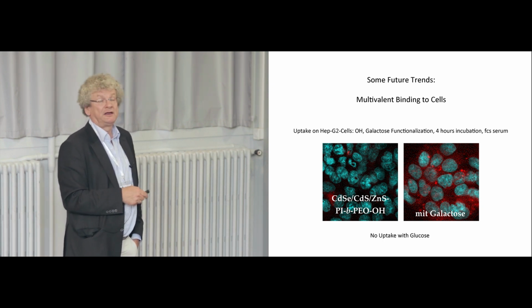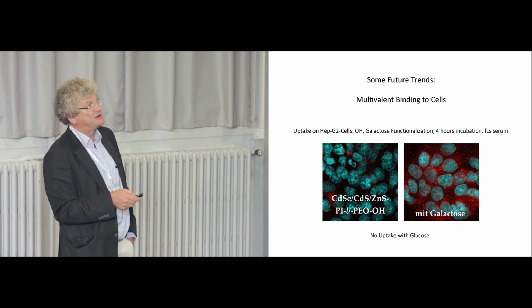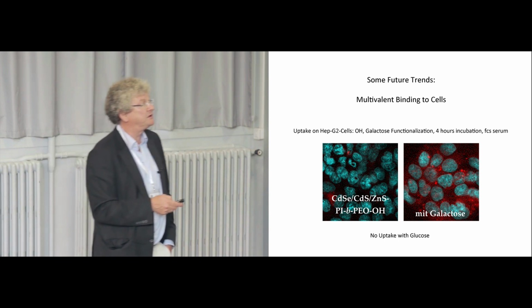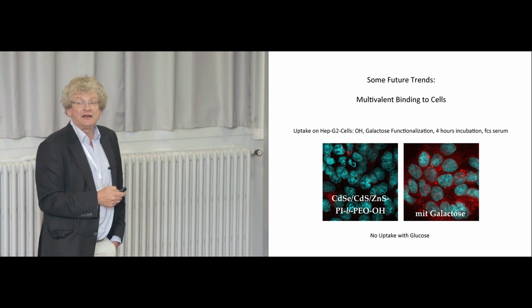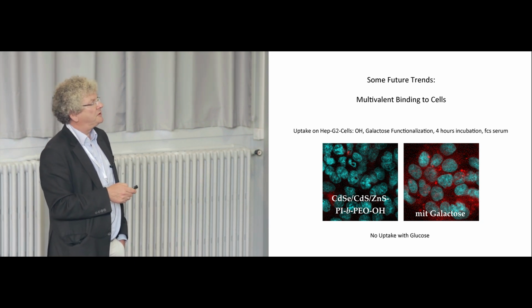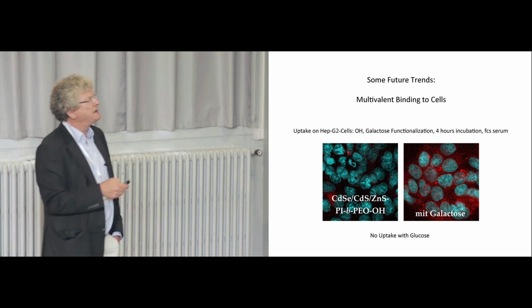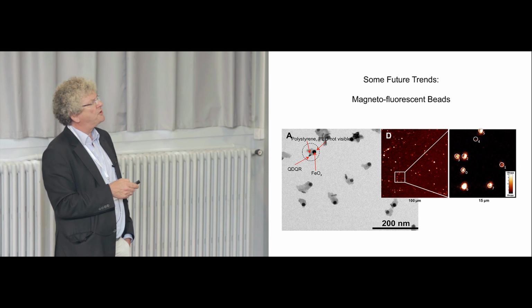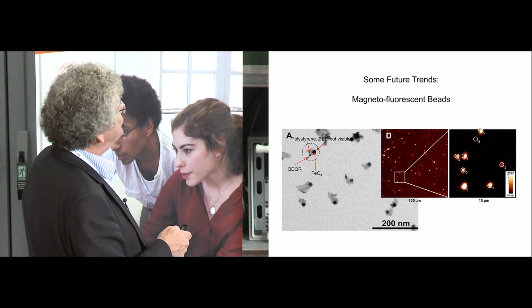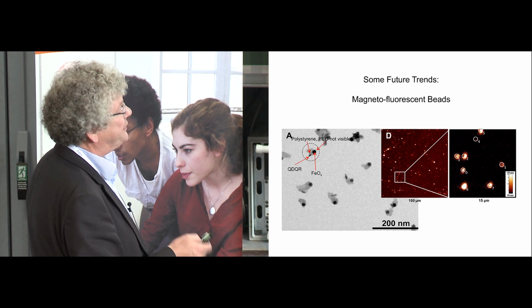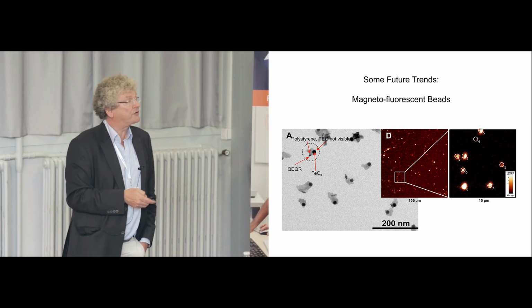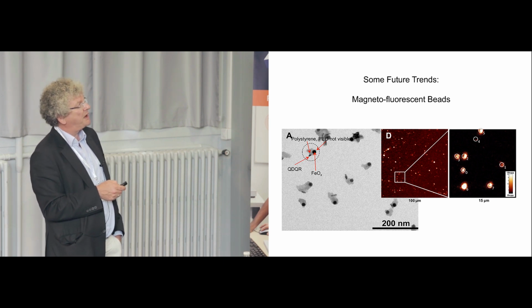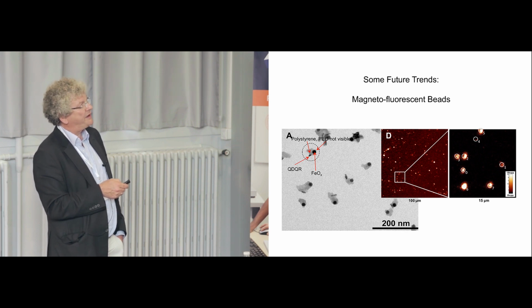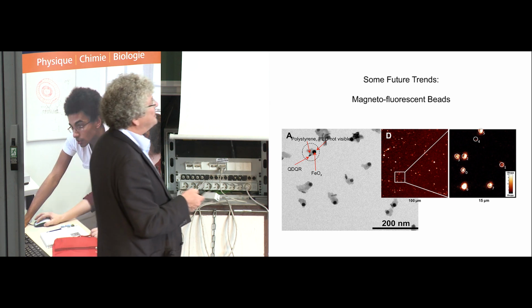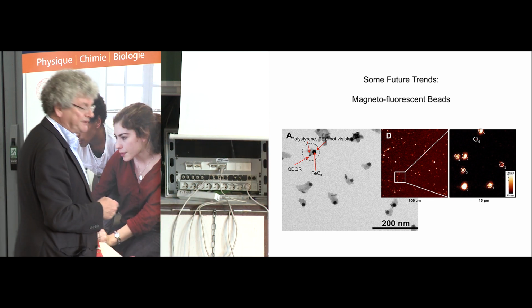For example, sugars play a big role. Here are some examples where we have specific uptake of sugar-decorated particles. Others is multifunctional particles. Here, for example, iron oxide with quantum dot quantum rods. This is not so easy because iron usually quenches the luminescence. We can see here in single particle microscopy images that in this case, where we apply a two-step encapsulation, first iron oxide with a small polystyrene shell, and then in the next step, these quantum dot quantum rods, then the luminescence is still retained in these systems.